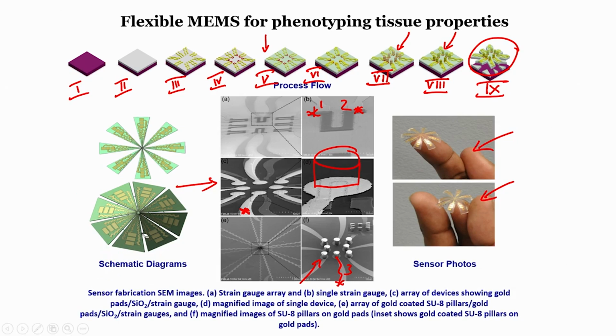Another thing that you need to observe is that the lines are not straight, these are wavy lines like this, you see the wavy lines, is it not? Why is it a wavy line, why not straight? Because if I have a straight line and I flex it, since the material is flexible, there would be a lot of stress in the film and the film will get cracked. To avoid cracks, we have designed the contact pads and the connecting lines in this particular fashion. So, all the things that we have been discussing are right in the center of this particular sensor, all right.